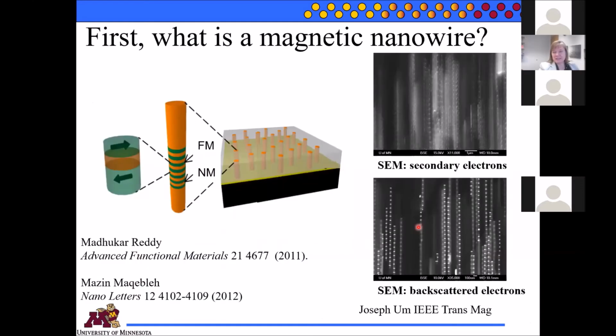So let's just really dig into what is a magnetic nanowire. This actually is work that was inspired quite a few years ago by the work of Albert Fert and his colleague Piraux in Belgium, where they were able to use anodic aluminum oxide templates to grow metal nanowires inside the pores. This is an oxide template.